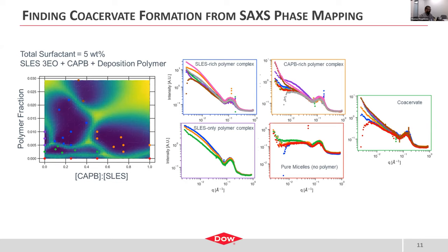And what we were able to do is map a number of different samples and then use a machine learning algorithm to generate similarity matrices to allow us to segment them into different regions of interest. And then using a priori knowledge and form factor modeling, we were able to identify each of those phases, where in this orange phase, you have the scattering patterns that are consistent with a CAPB rich polymer complex. The blue phase, a SLES rich polymer complex. We're able to identify pure micelle phases where there's no deposition polymer present. We're able to show where there's only SLES and polymer complex forming. And then most importantly, we were able to show here in the green several areas where we could actually form a coacervate phase and therefore generate regions of deposition as we continue making newer formulations.